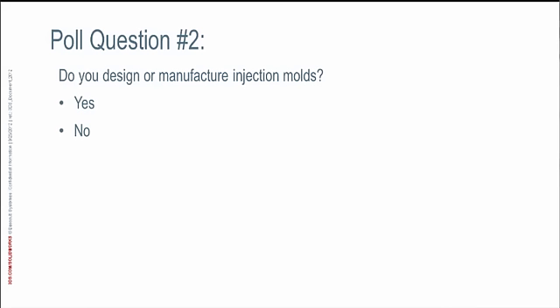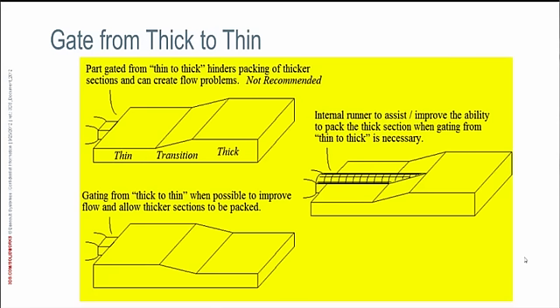If it's injection molding, a mold has to get designed and manufactured, so it's important to take into account considerations for the mold itself. One of the primary things you want to do is always make sure you're gating or flowing from thick to thin. We already talked about how plastic melts like to take the path of least resistance — that's always the thickest area. If you're gating from thin to thick, you can get cooling effects in the thin sections, causing the thick section to be underfilled and under-packed. That can cause all kinds of problems: parts more likely to warp, or sink marks.